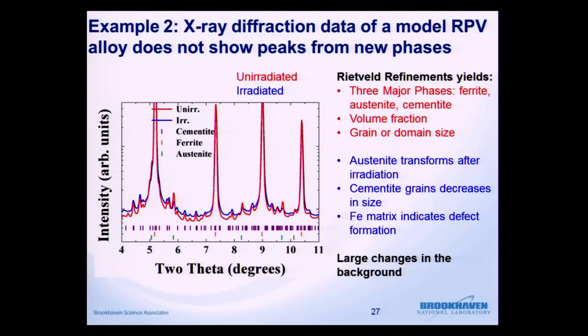Now, for my second example, I'd also like to talk about some of the new science that's coming out of these experiments. This is X-ray diffraction data that we took on the model RPV alloys. These peaks are diffraction peaks, and they're sort of a fingerprint for the crystal structure of the material that I showed you earlier. So by identifying these peaks and matching them with known peaks, we're able to identify the phases in the material. The red line is unirradiated material, and the blue is irradiated material.